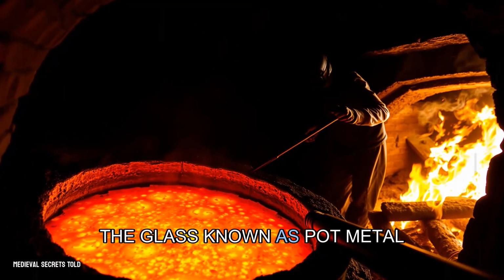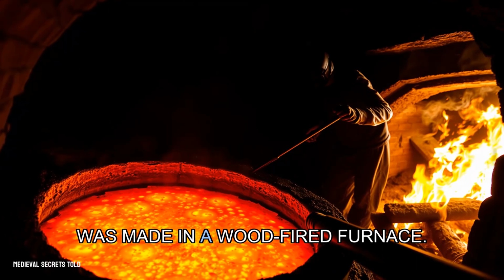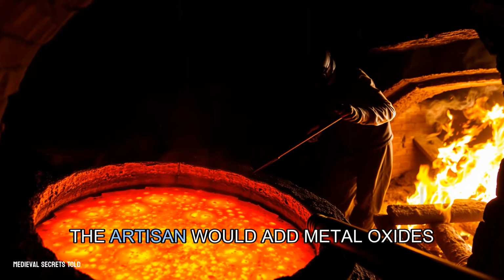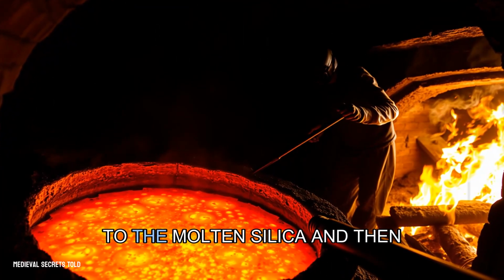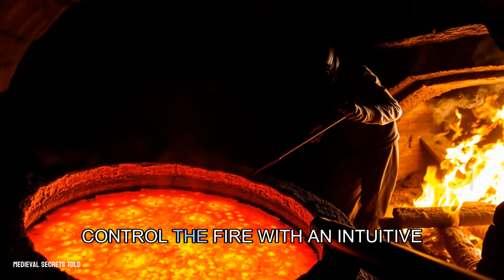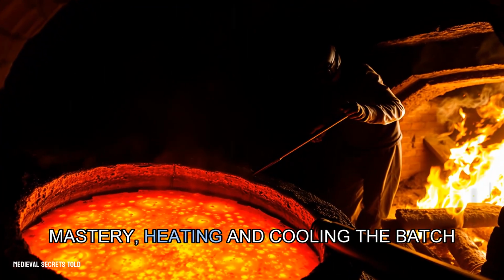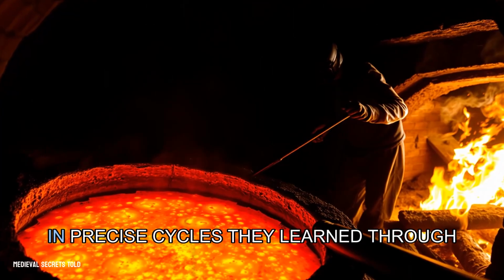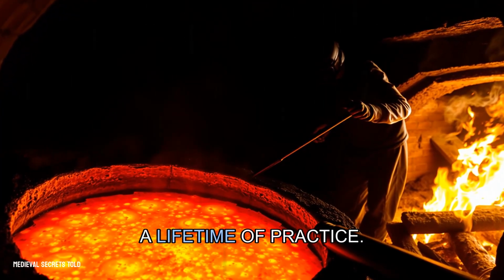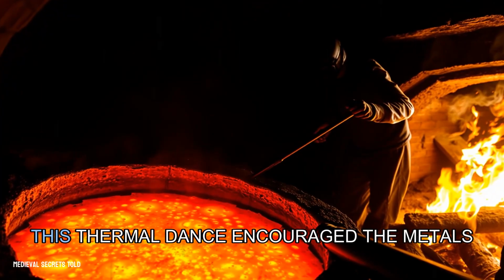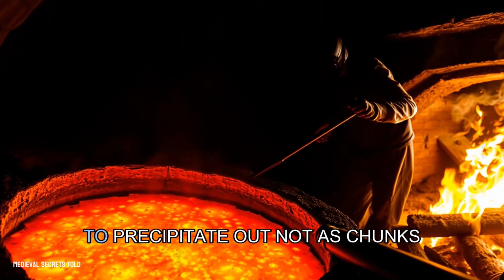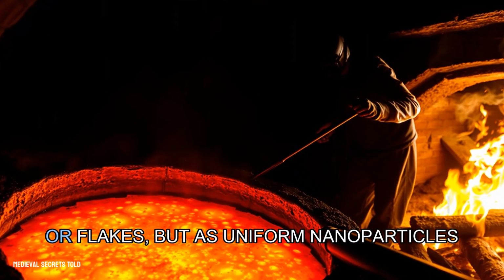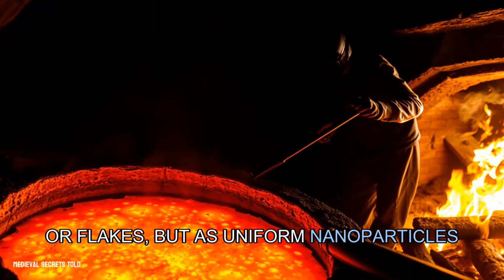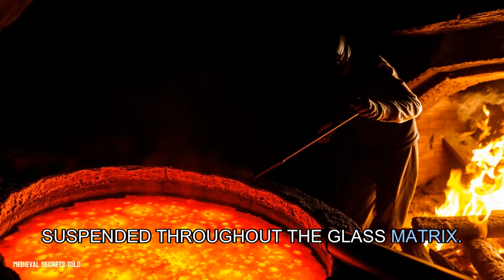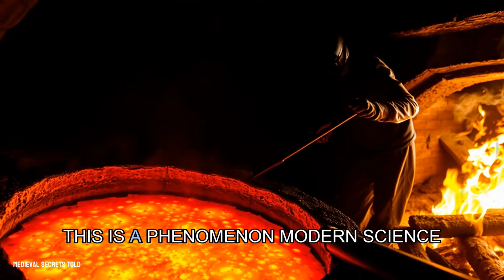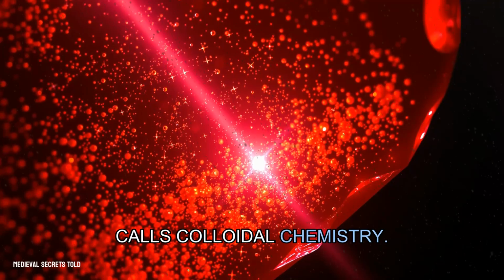The glass, known as pot metal, was made in a wood-fired furnace. The artisan would add metal oxides to the molten silica and then control the fire with an intuitive mastery, heating and cooling the batch in precise cycles they learned through a lifetime of practice. This thermal dance encouraged the metals to precipitate out, not as chunks or flakes, but as uniform nanoparticles suspended throughout the glass matrix. This is a phenomenon modern science calls colloidal chemistry.